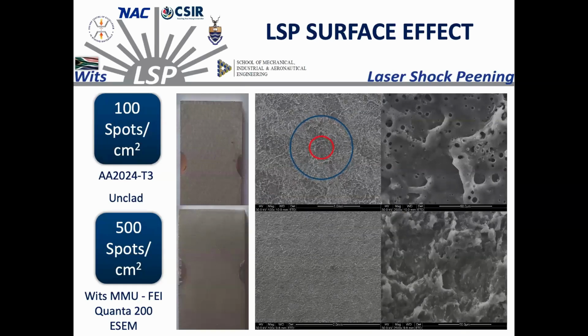At the low coverage, what we see is that the spot, which is indicated by that blue circle, is still quite obvious, so we can still spot the actual spot size, but there is an internal area where the overlap basically doesn't happen, where we see some tiny features that, apart from the evident remelting of the surface, include a little bit of cavities that are even more evident on the surface.